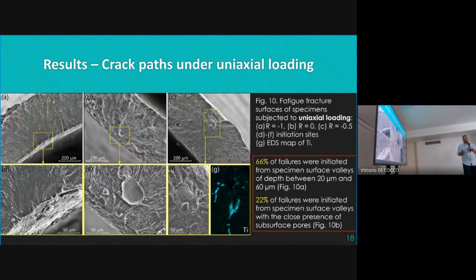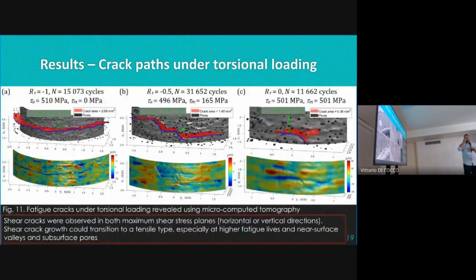In other tests, we found a way to get rid of most of the pores, but again, no actual impact on the fatigue life. The valleys are much more important, I would say. From the tomography, we can see for the torsional test, because the valleys were very important for the moments where the actual stresses were the reason for the specific crack. For torsional stresses, it was more like the crack was between the layers. It was going around the specimen.